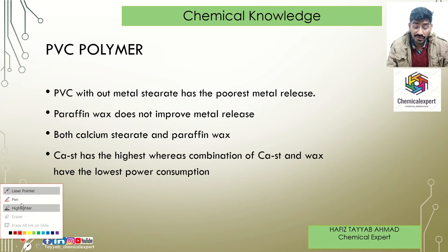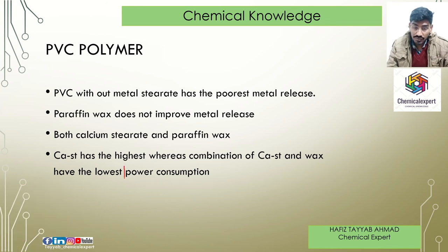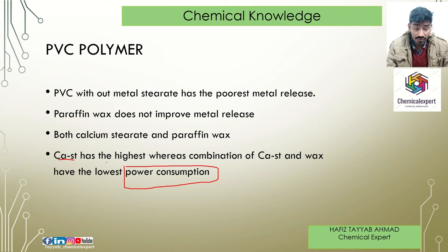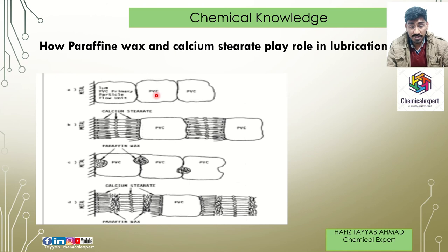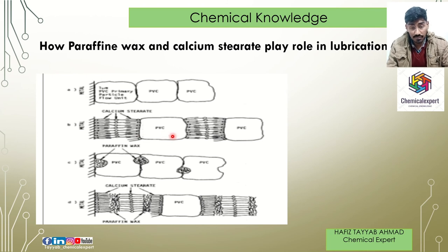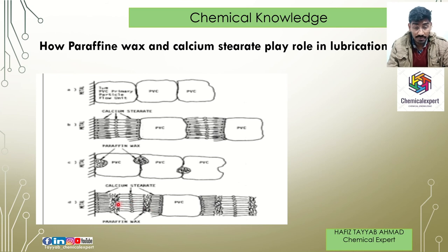Power consumption is an important point to understand. When we use only calcium stearate, the highest power consumption occurs because external lubrication is absent. When we use both calcium stearate and paraffin wax together, the lowest power consumption is achieved. We cannot neglect either one. Calcium stearate helps between PVC molecules — internal lubrication — and paraffin wax acts as external lubrication between molecules and the metal surface.